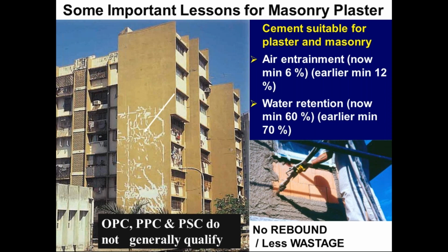If you take a look at the specification and standard of the masonry cement, you will be surprised that in the earlier days, a few years back, before the masonry code was revised, it was regulated air entrainment minimum 12%. Later on, after the revision, I don't know for what reason, they reduced the specification to 6% instead of 12% minimum for air entrainment. And the water retention, there's a method of testing, which was earlier specified as 70%, now reduced to 60%.